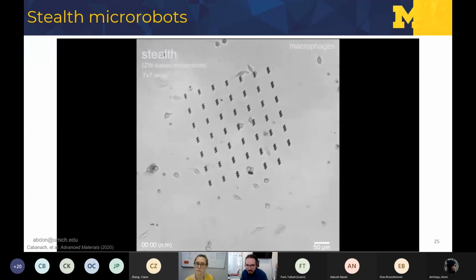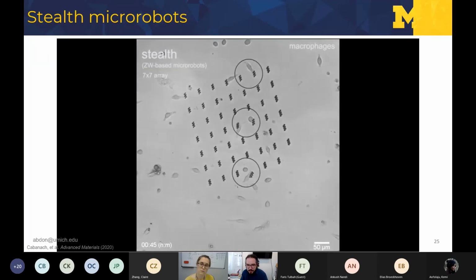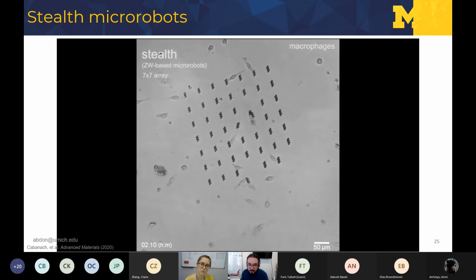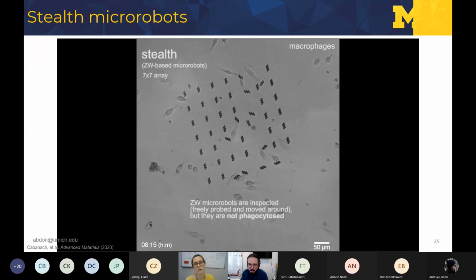So we can see that there's no phagocytosis over many hours, up to 90 hours of co-culture with these robots. And you can see here that even in some of them, they're exhaustively inspected, but we don't see any recognition and uptake from the macrophages.